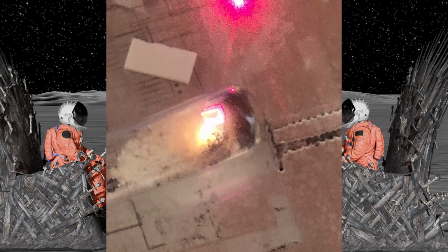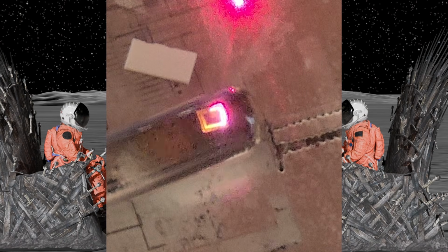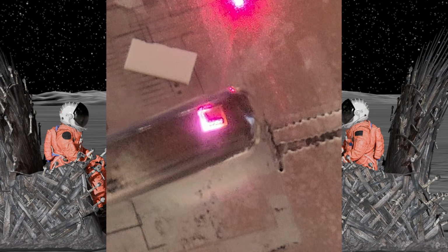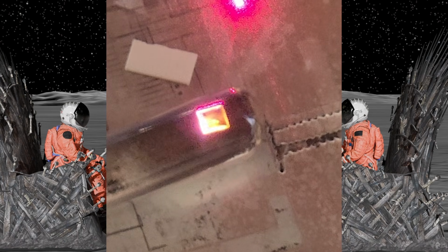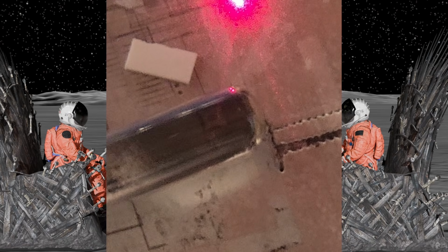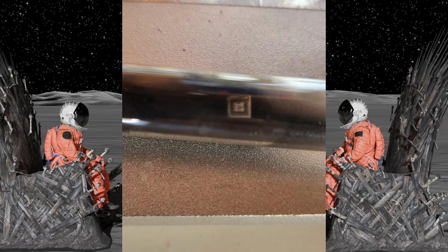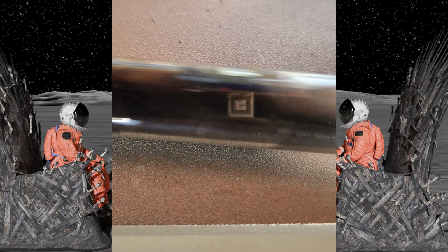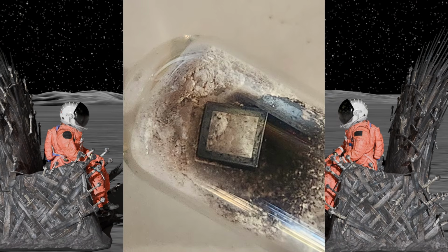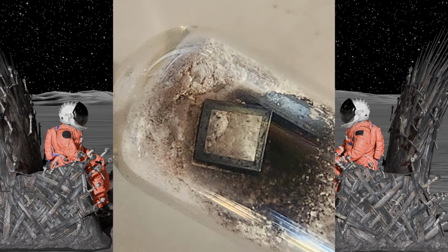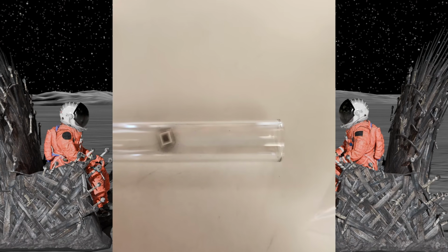So I took titanium and iron, tried them individually, and then we mixed them together. Basically had them one side of the test tube iron monoxide, the other side titanium dioxide, and we were able to reduce both of them in the same tube using different settings while they were in intimate contact with each other, which was kind of impressive. The iron showed electroconductivity. The titanium, not so much. It was in the mega ohms, if not, it was not exactly conductive.